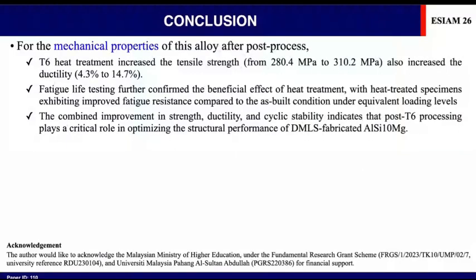In conclusion, after T6 heat treatment, the tensile strength and ductility of this alloy are improved. At the same time, the fatigue resistance also improved compared to the as-built condition under equivalent loading level. And lastly, the combined improvement in strength, ductility, and cyclic stability indicates that post-T6 processing plays a critical role in optimizing the structural performance of DMLS-fabricated AlSi10Mg.